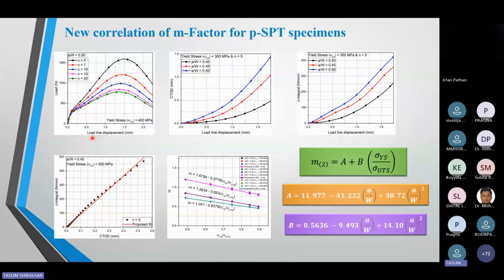So I used the second correlation, and based on this, I generated M versus sigma yield stress upon sigma UTS. I observed that I am getting a linear correlation between these two parameters as a function of a/W. So I proposed M2, meaning I nominated the second equation, so I'm calling this M2. M2 is a function of A plus B into this ratio, where A is a function of the a/W ratio and B is also a function of the a/W ratio. And this type of correlation is available for the standard specimen.